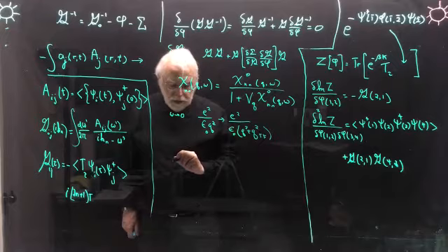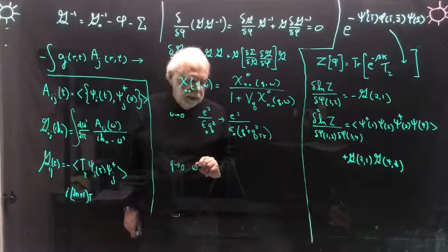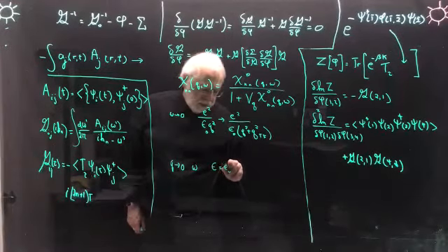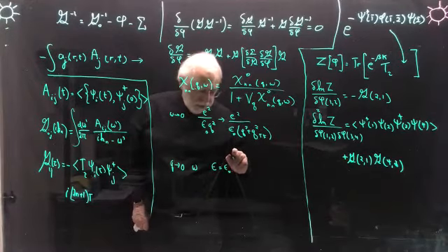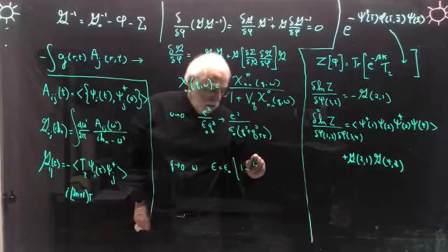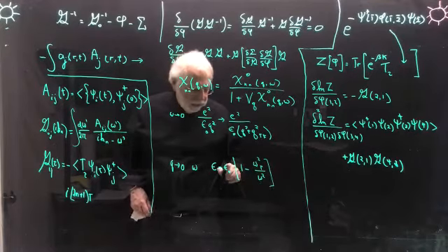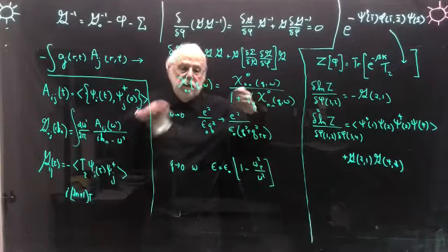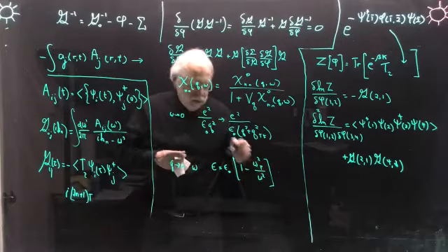But on the other end, if q goes to 0, and we look at finite frequency, then epsilon becomes epsilon_0. Again, epsilon is this denominator. And we proved that it is epsilon_0 times 1 minus omega squared plasma divided by omega squared. And so it means that the dielectric constant goes to 0. So it means that we have oscillation at the plasma frequency, when omega is equal to omega plasma.